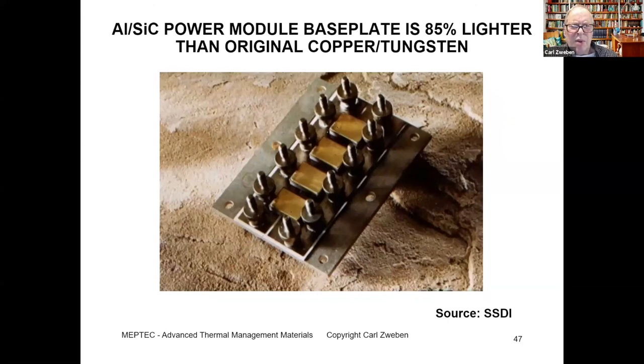This is a good example of the weight savings potential with advanced materials. We actually used a module like this in one of our GE spacecraft. So it's a power module. The original base plate was copper tungsten, and the manufacturer replaced the copper tungsten with ALSIC with a weight savings